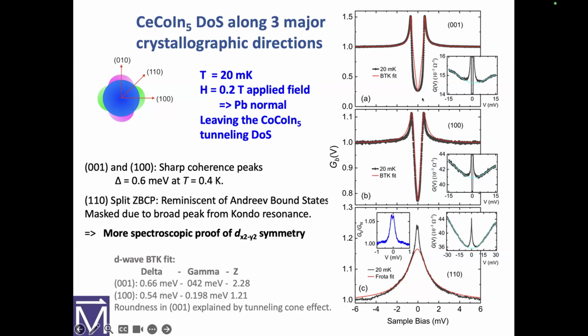And so here's an example of the 001, or C-axis, tunneling. The lead is driven normal here, so we are only seeing the gap of the cerium cobalt indium 5. And here's the 001 direction, the 100 direction, and the 110 direction. I'm going to back up about this 110 direction.